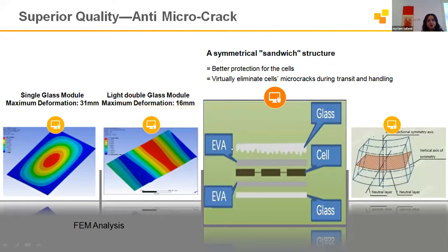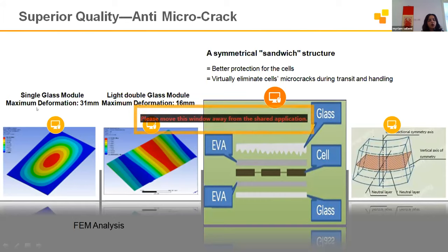Here you can see two differences when comparing. It's the superior quality anti micro crack. So here, the normal one versus the double glass one. With the double glass, we see less impact regarding micro cracks. Here, the super quality, same thing. For example, the single glass model maximum deformation is 31 millimeter, while the double glass is only 16 millimeter. So we can notice the difference between the two models here.